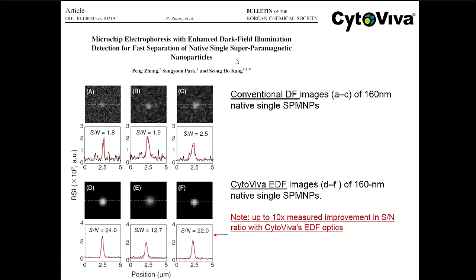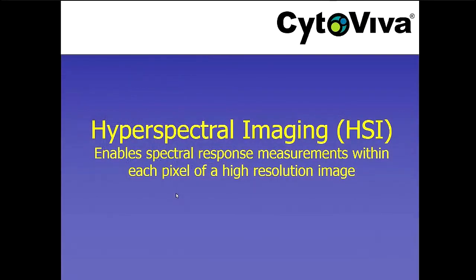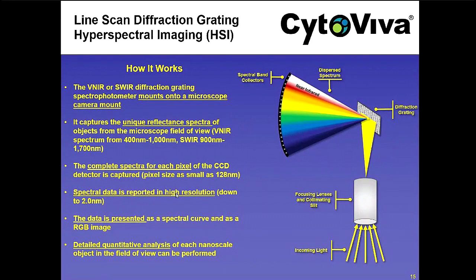If you try to look at how that manifests itself, this is a paper that was published by a group that's been a longtime user of these dark field optics in Korea, where they are conducting microchip electrophoresis. They've been using these enhanced dark field optics for a number of years and getting very high signal to noise images, which qualitatively you can see here of their iron oxide nanoparticles in this experiment. But they decided to run an experiment where they would use standard off-the-shelf dark field optics and compare the two. From a qualitative perspective, you can see a dramatic difference in signal to noise, but also quantitatively, when they measure that signal to noise versus standard dark field optic, they see about a 10x increase in signal to noise. So that gives you a sense of how these dark field optics can improve the experience of looking at, in this case, nanoparticles and cells.